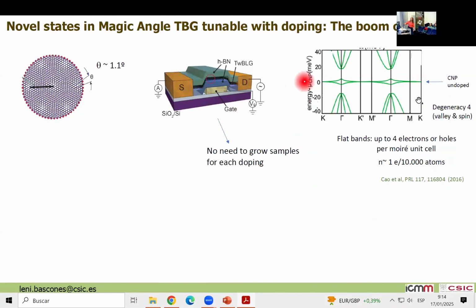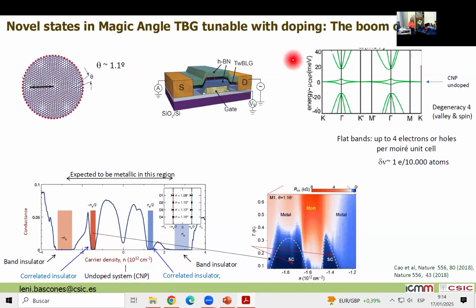So then we can, these ones, we can have up to 4 electrons or 4 holes. Now, you can see here, this state is expected to be metallic up to filling 4 or up to filling -4, right? Because we have a band that is crossing the Fermi level. What Pablo saw is that you have this insulating state. This is -4. This is in 10 to the 12, but this is -4. This is +4. Not this one. This is +4. So that's okay.